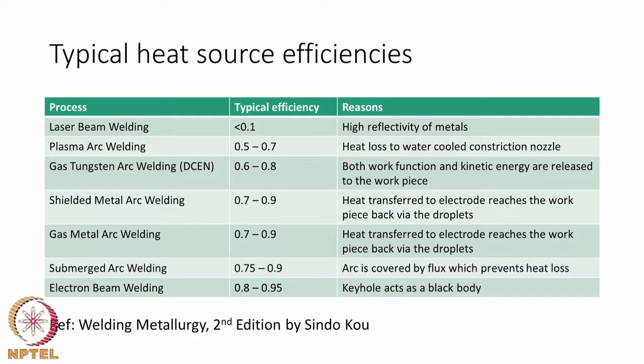And we do have also GMAW showing very good efficiencies, and normally GMAW is with electrode positive polarity. The reason why efficiency is considered high is because the electrode actually melts, and those molten droplets of liquid at high temperature reach the base material and give the heat. So, in other words, the heat that is given to the base material and also to the electrode both reach the base material eventually, and therefore, the efficiency of GMAW is very high, reaching up to 0.9.